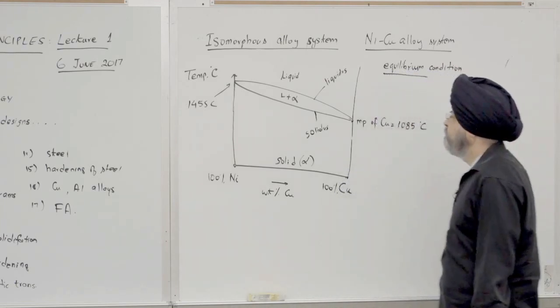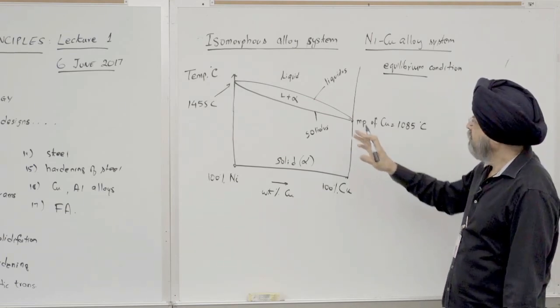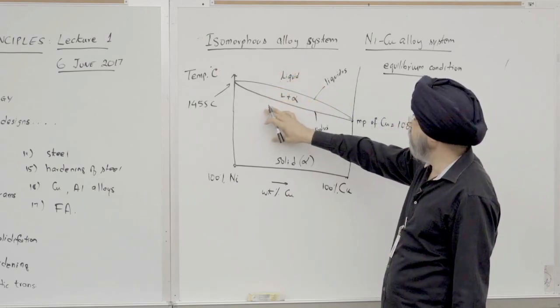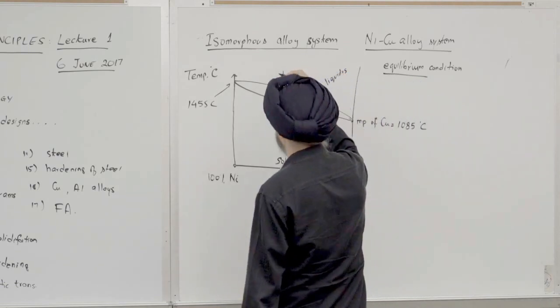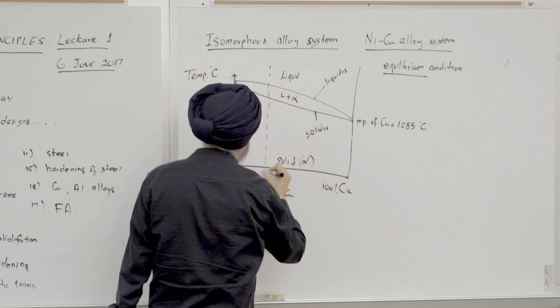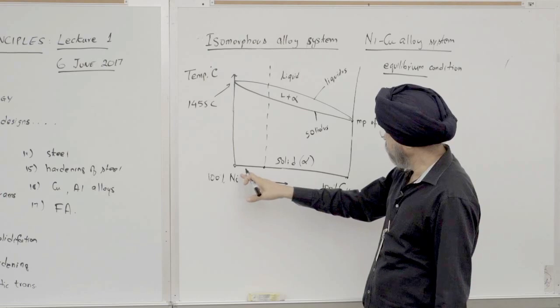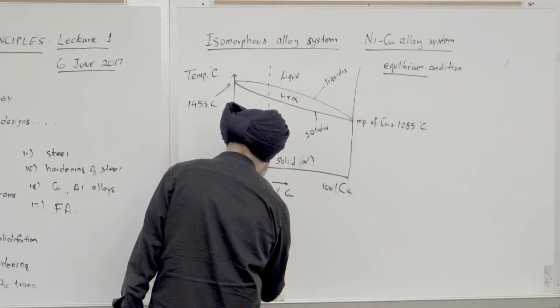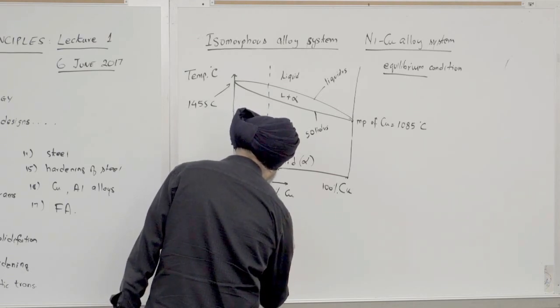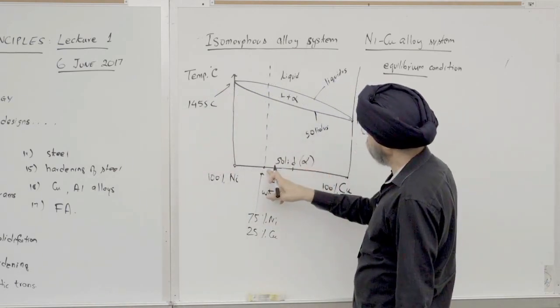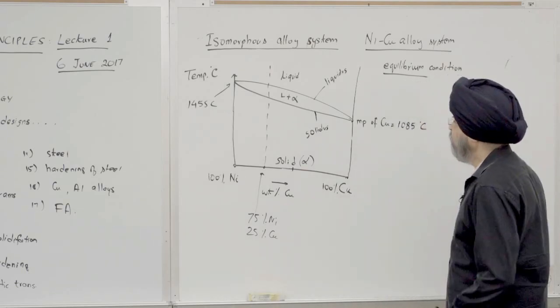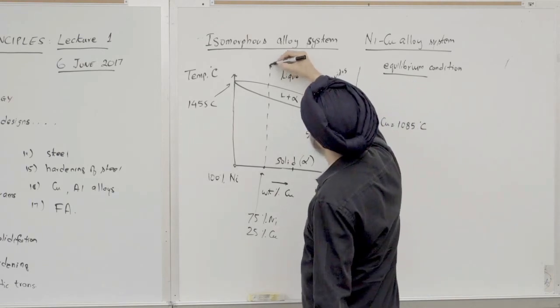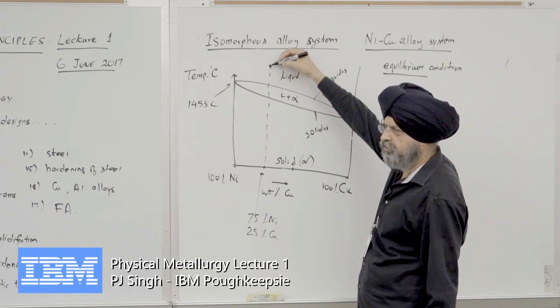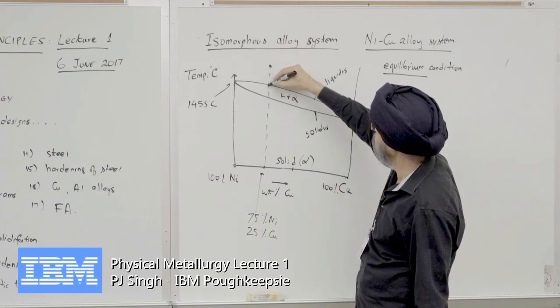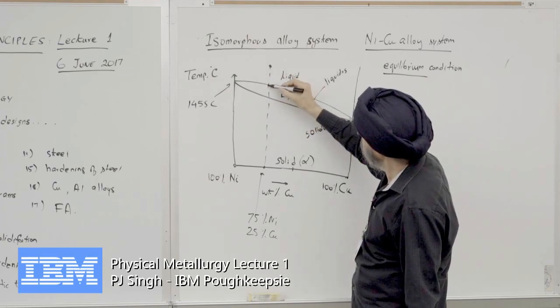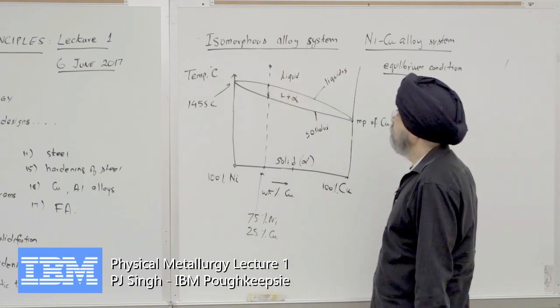So what does equilibrium mean? Equilibrium means that we are cooling this very, very slowly. Let me take a composition. Let's say this composition would be, let's say, 75% nickel and 25% copper, right? Because this is 50-50, so this is nickel rich and has less copper in it. If I take this composition and start off at this temperature, here the alloy is a liquid. So we start cooling it slowly, slowly, slowly. We get to this point. At this point, as we come down, we start getting solidification. At this point, it's completely solid.